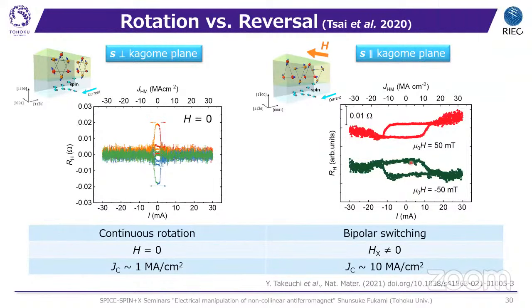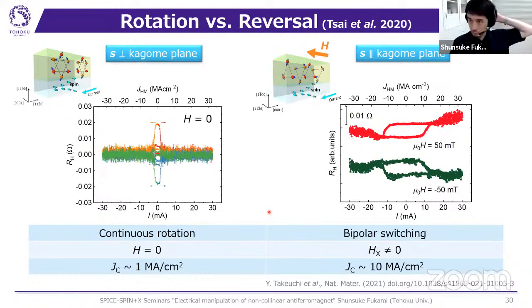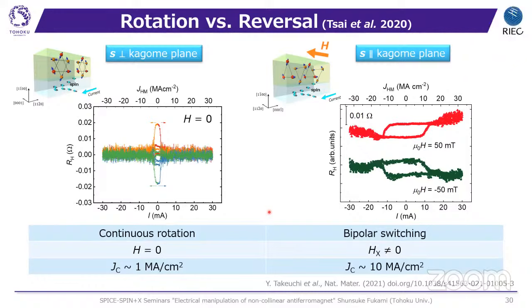Okay, Mr. Rajan has two questions. Yeah, so go ahead. Yeah, thanks, Professor Fukami. I have two questions. Firstly, do you expect similar switching mechanisms in cubic systems like manganese 3 nickel nitride? I think so. As long as you can inject the spin current perpendicular to the non-collinear spin structures, I think you can also observe the chiral spin rotations. The point is the configuration: the accumulated spin should be perpendicular to the non-collinear plane. Okay. So if we take into consideration the Kagome plane, then you would expect similar behavior.